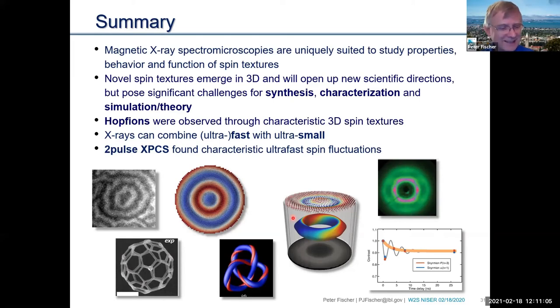I mean, it's called transmission X-ray microscopy. The transmission of soft X-rays is limited by physics, by nature. We can't change that. And therefore, you still have to put them on a substrate or thin the area down like you do with the TEM. I always like to say the TEM has similar challenges to the TXM, and they're actually about the same. It just replaces the E by an X, but the penetration power of electrons is almost the same as you would have with X-rays, soft X-rays, not hard X-rays.